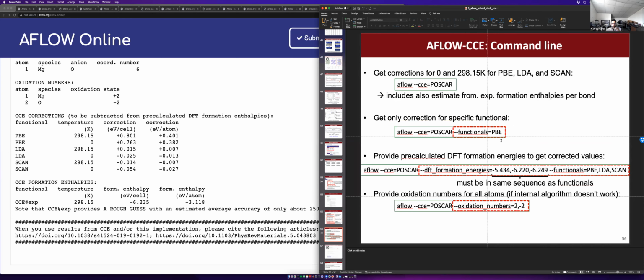And you can even select particular functionals. Let's say you didn't want it for all the functionals, but you wanted just a particular functional. And then you can also input, if you've already done the calculation and gotten the formation enthalpies from DFT, you can actually give it as an input. And then instead of getting a rough estimate of the formation enthalpy, you can get an exact formation enthalpy, or exact to within our correction here. And you can also provide the oxidation numbers for the atoms. Let's say if CCE did not calculate the oxidation numbers correctly for you. So you can actually force CCE to do it for a particular coordination.